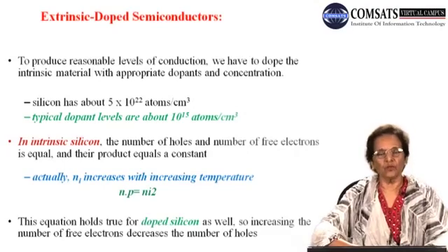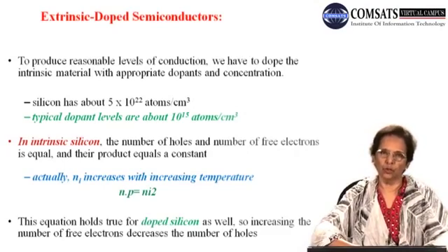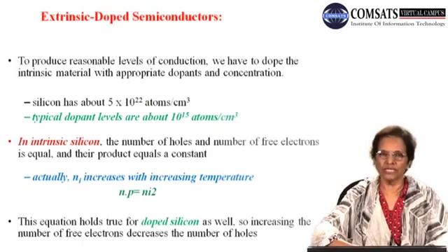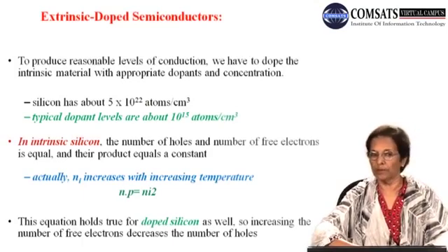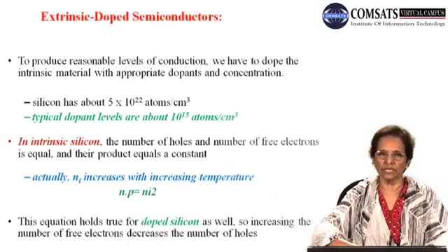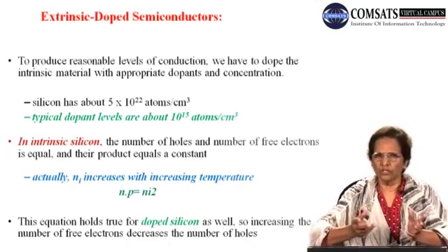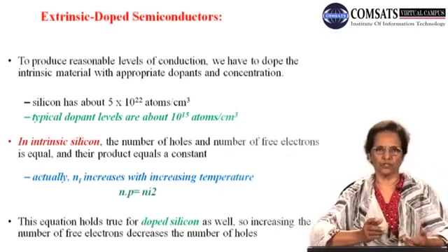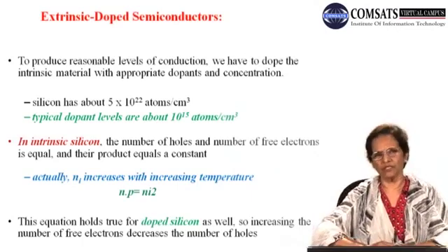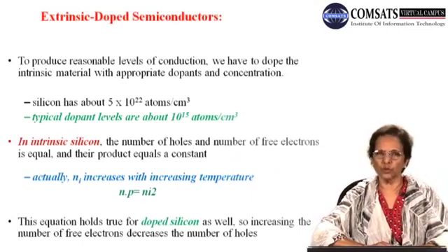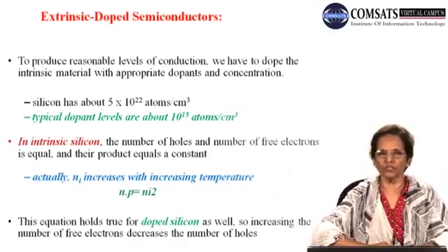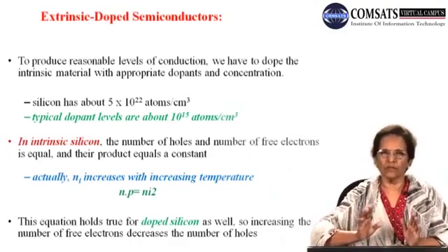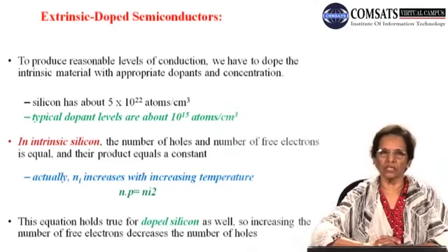Obviously, we would like to add dopants. Why? Because we want to increase the carrier concentration from the pure material or the intrinsic carrier concentration. Your intuition would be to enhance the dopant concentration as much as we like. But that cannot happen, because if you increase the dopant concentration to the level of the host silicon crystal, then you will end up destroying the silicon crystal structure itself.